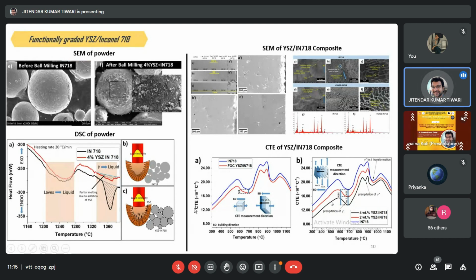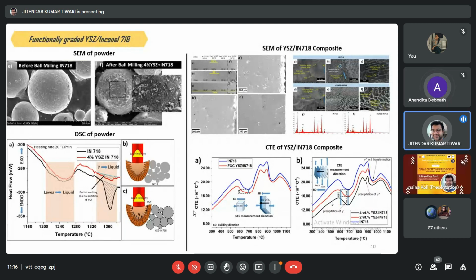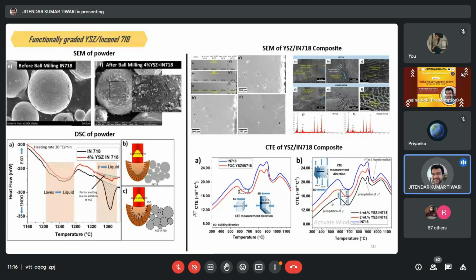CTE is basically the coefficient of thermal expansion. What is happening is that when we heat any material, obviously it will expand. Why is it expanding? Because the lattice parameter is changing. There might also be some phase transformation. For example, in the case of steel, it changes from alpha ferrite to gamma austenite, and then it changes to delta ferrite. So these kinds of phase transformations are there.